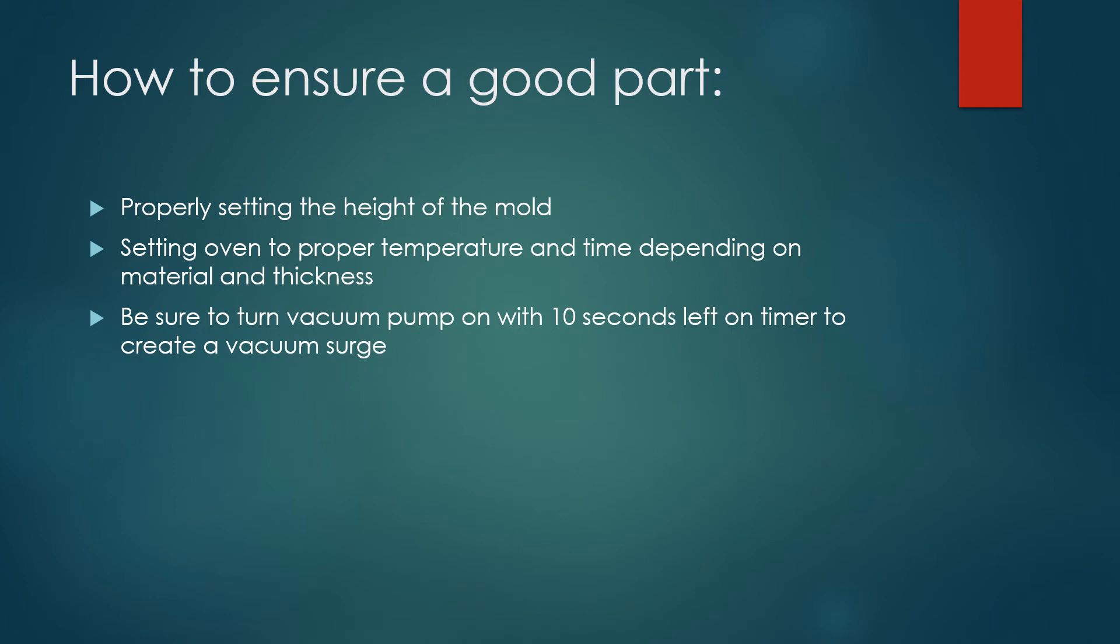It's adjusted by those bolts on the bottom, but that seems to be something that in the video was having to be adjusted constantly. It even caused the defect on the first part where it had a little tear in the side from it being too high. So that's just something you want to get set right off the rip and make sure it's the right height, but also make sure it isn't causing any defects.